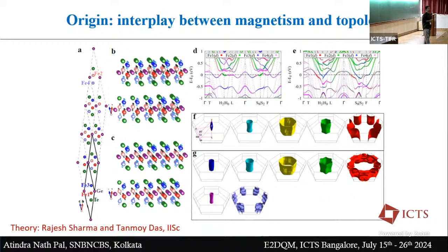So near the spin reorientation, you have a sign change in the Hall data, right? There is a Fermi surface reconstruction. It's already difficult to do DFT calculations in this kind of ferromagnetic metal. But what they predicted is that there are two energetically very close phases available. One is the collinear and another is the non-collinear phase, and the energy difference is only 10 millielectron volt, which is close to 100 or 120 Kelvin or so. These are not the only possibilities, but these are two possibilities. And when they calculate the electronic structure, they see that in the non-collinear phase there is an appearance of new Fermi pockets, and that can explain our Hall data. But that cannot explain the low temperature phase transition that we are observing. So there are a lot of unclear things in this kind of material itself.